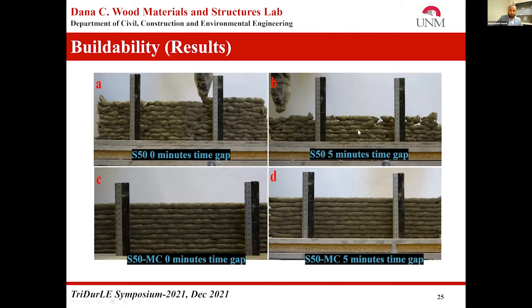And at 5 minute time gap, due to more time gap between the filaments, this mix was stiff enough that it was not extrudable anymore after printing the 6 filaments. But if we compare with the addition of MC, the same mix was flowable enough that it could be printed even after the 5 minutes time gap.